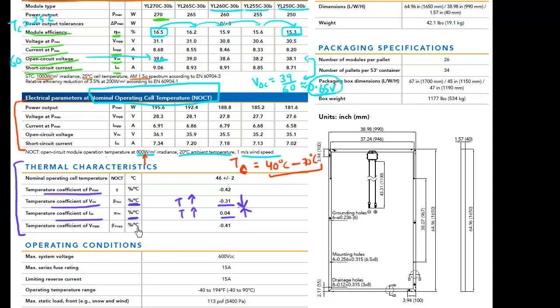The overall power of my cell essentially decreases. And you can see that my power decreases with this negative temperature coefficient of 0.42 percent. And sometimes they also specify the nominal operating test conditions. So they say that if you do operate the cell at this irradiance level of 800 watt per meter squared. And this is the temperature of the ambient and this wind speed. The temperature of the cell is going to be between 46 plus minus 2 degrees centigrade. So it's going to operate between 44 to 48 degrees centigrade.